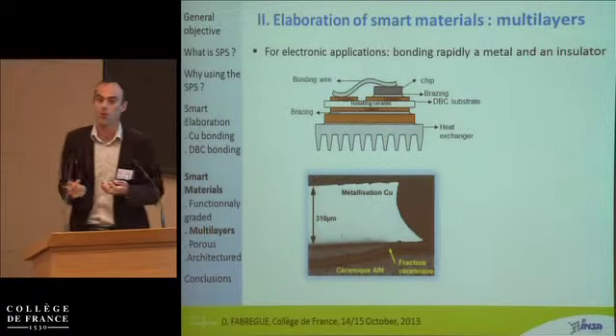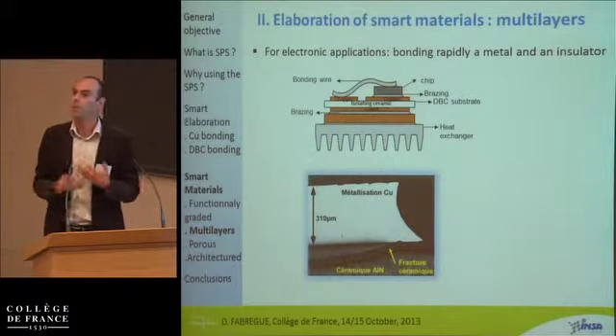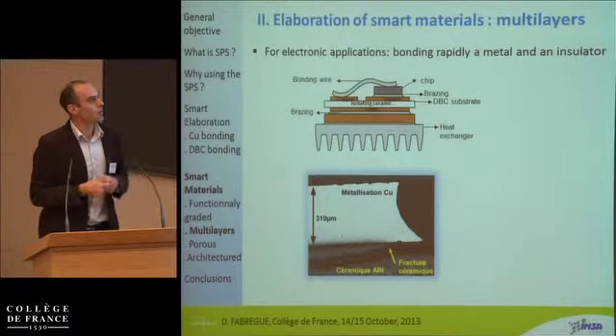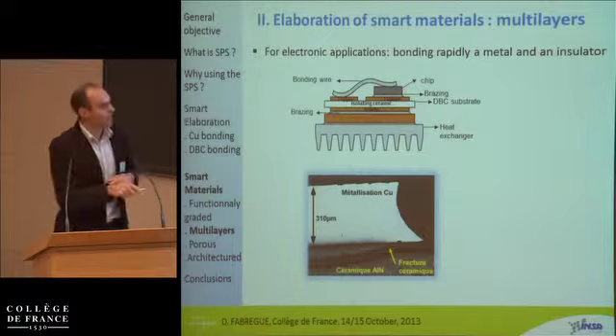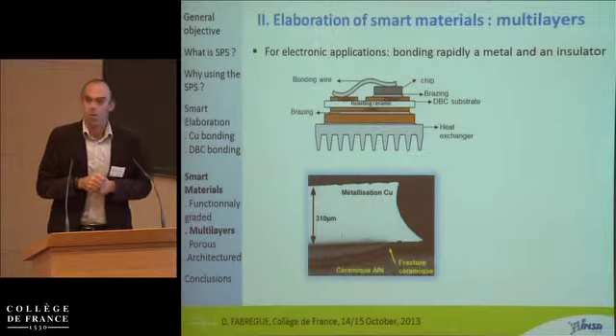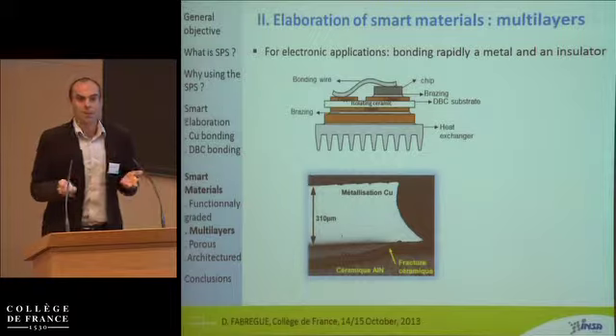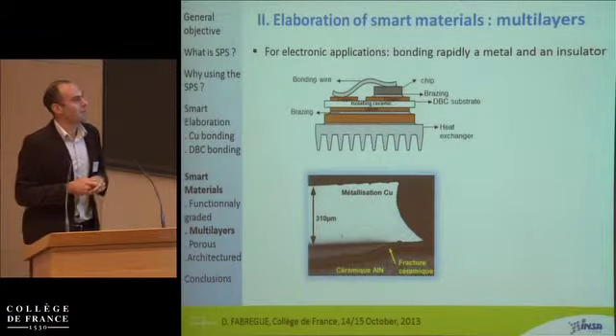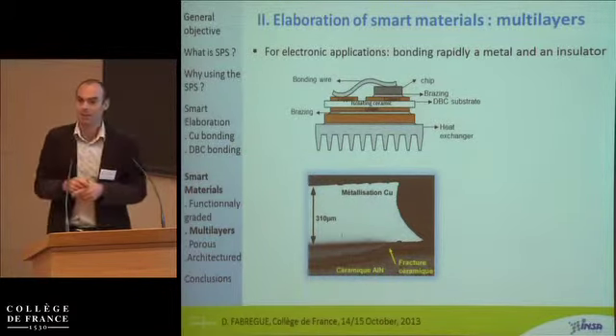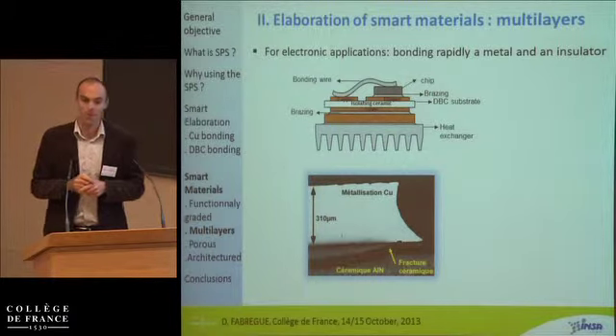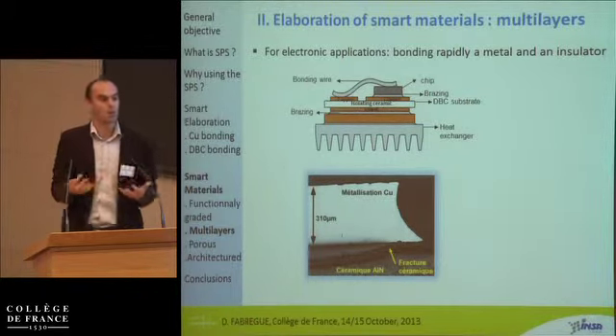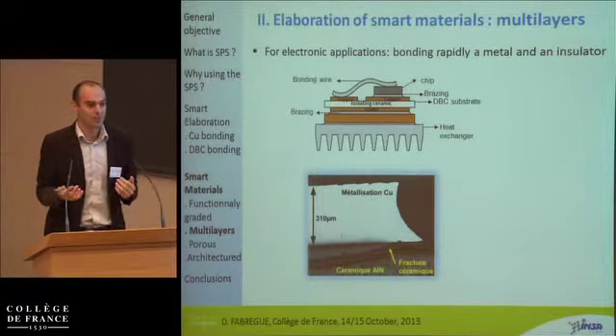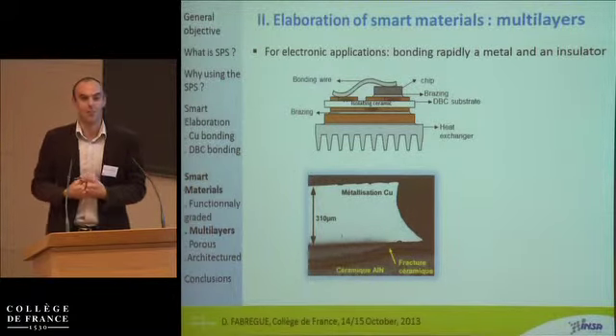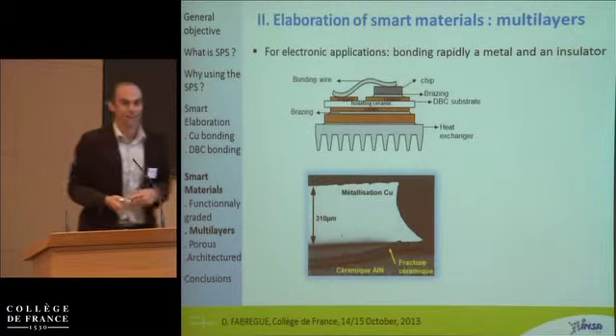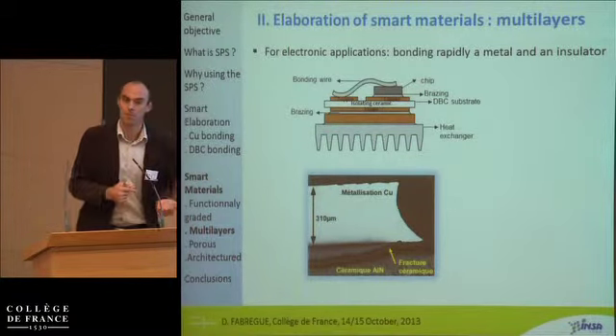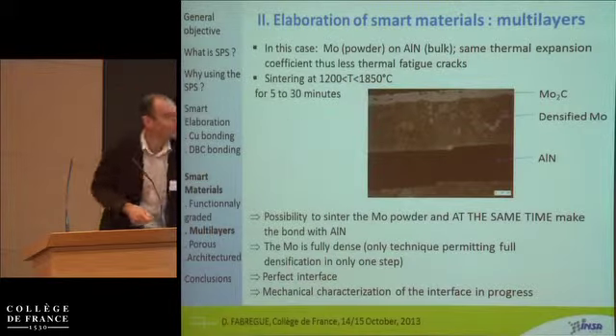So we thought about whether we can replace one of the two materials in order to avoid that kind of problem. If you look at the database, one material which has quite the same thermal expansion coefficient as aluminum nitride is molybdenum. Now you have a big problem, because molybdenum has quite good electrical properties, but it's really difficult to get. It's a refractory metal. But as I said in the introduction, SPS permits us to get refractory metals. So this is what we've done.